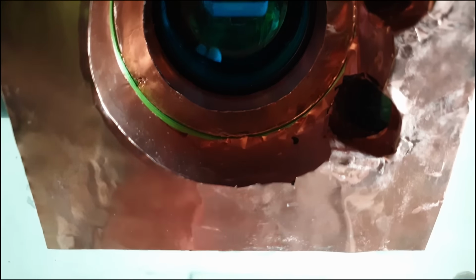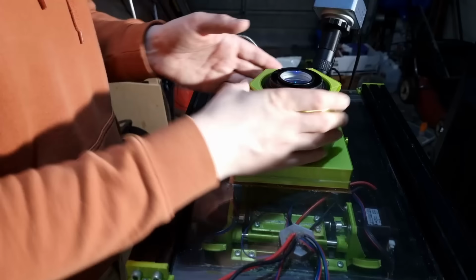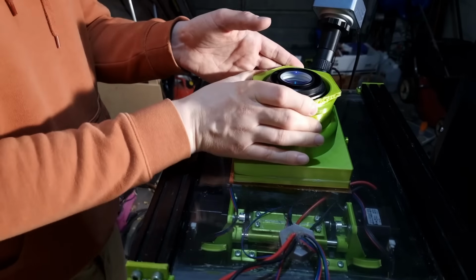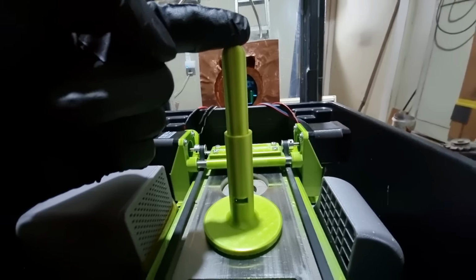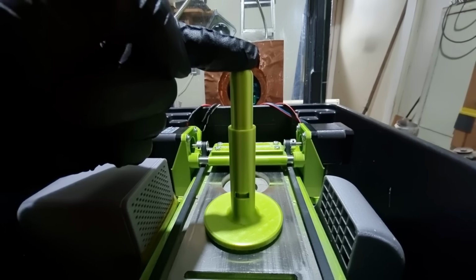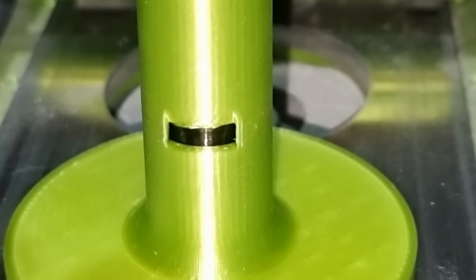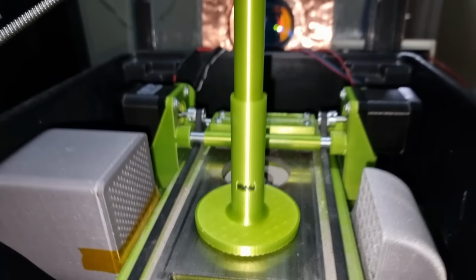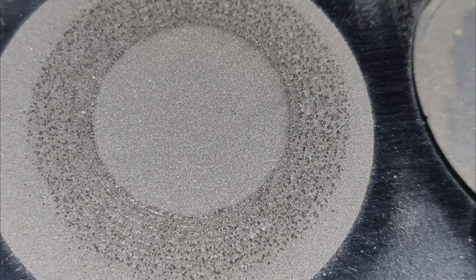Moving forward, one of the first stumbling blocks in getting this off the ground involves setting the correct distance between the f-theta lens and the powder bed. Because I wasn't using an established control card, I couldn't simply reference the size of a projected image, and therefore made a tool which would sit flush with the powder bed. I didn't really have much luck with this, and I suspect this came down to several factors, the flimsy nature of the plastic container and my inability to load it correctly while adjusting the height being at the fore of them. I also tried projecting an image down onto the powder bed, but this didn't yield the result I was looking for either, potentially for the same reasons as before and the differences in wavelength.